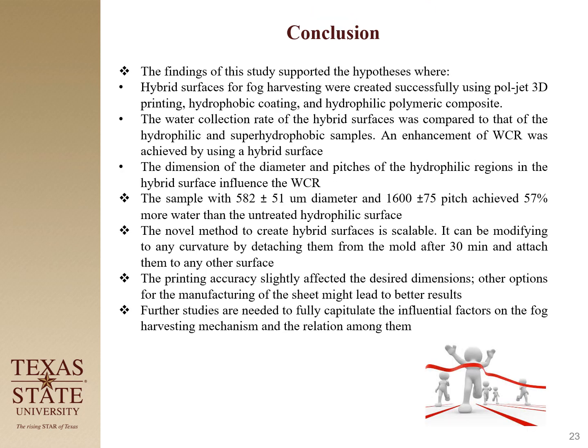In conclusion, the hypothesis is fulfilled through making a hybrid surface, and that hybrid surface was making more water than non-treated surfaces and the superhydrophobic. And I can show that one of the samples, at one of the ratios, was giving 57% more water than the non-treated one. Changing the dimension of the diameter and the pitches was influencing the water collection rate.